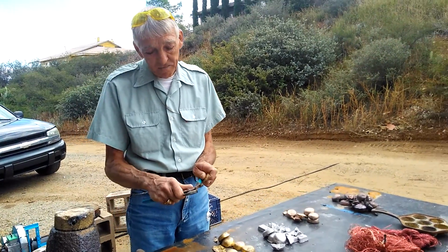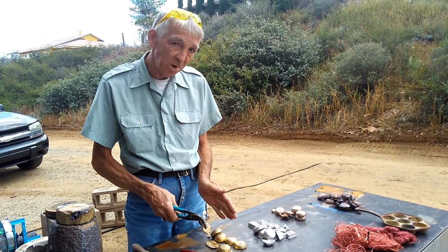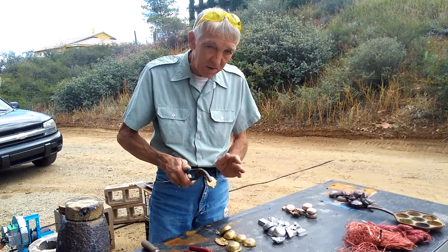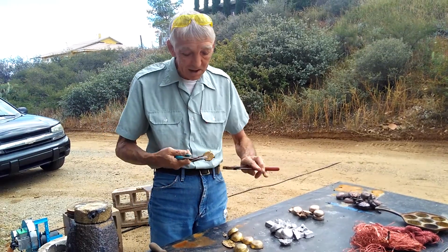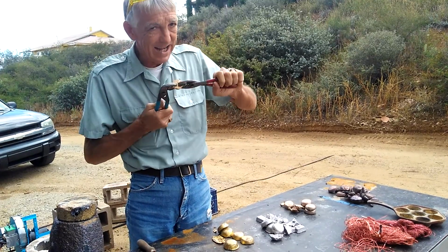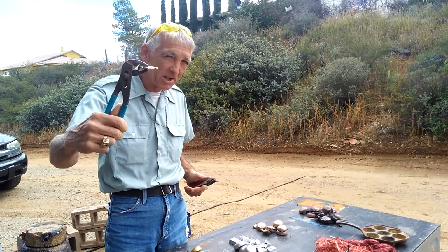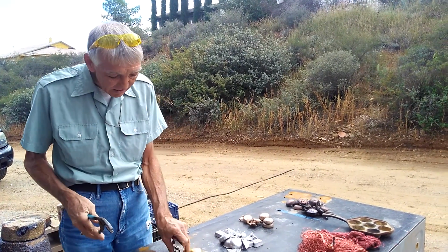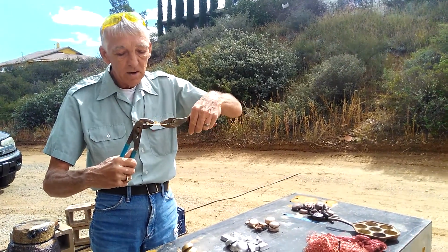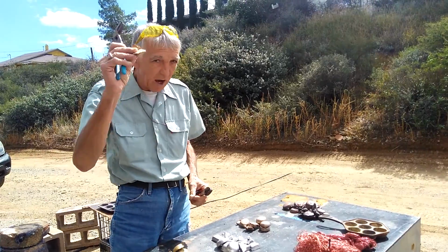No, we got the right, by dumb luck, we got the right mixture here on the first pour, having thrown somehow the right amount of aluminum in with the copper, inadvertently. In that, I cannot lay down on this and break this little, it may be 3/16 thick. Here's another piece. It's a little bit more malleable, and you can bend it, but it does not break. So I think we got a perfect mix here.